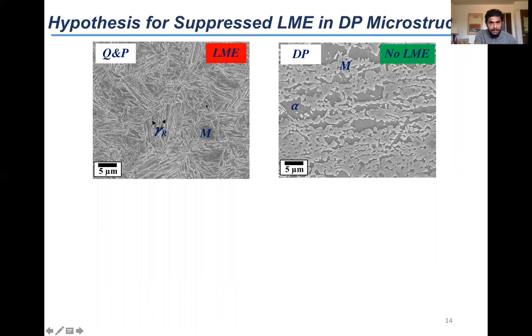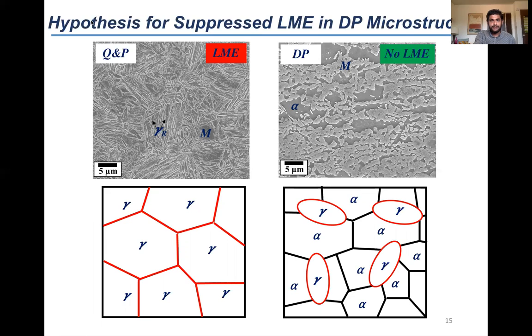So here is the QNP microstructure. Here is the DP microstructure. The QNP microstructure has martensite and retained austenite. The DP microstructure, which did not crack, had martensite and ferrite. Now, in order to understand why these two microstructures have different LME behavior, we have to first understand how these microstructures were produced. The QNP microstructure was formed by full austenitization, whereas the DP microstructure was formed by intercritical annealing. So the high temperature microstructure before the QNP or the DP structure was formed was fully austenite in the case of the QNP steel. It was ferrite and austenite in the case of the DP steel.